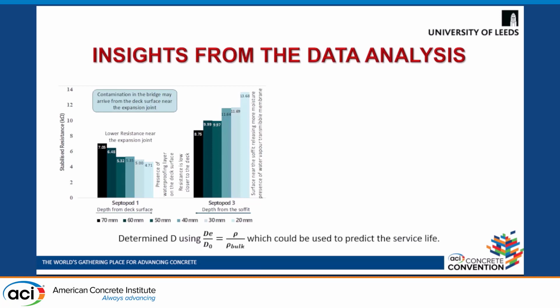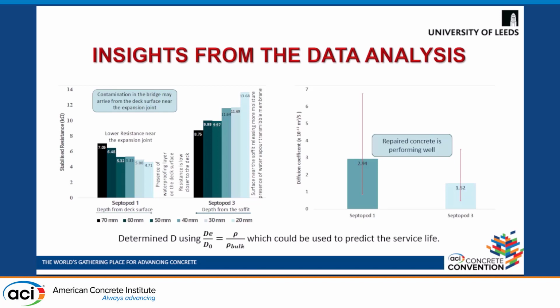Therefore, these obtained values of stabilized resistance can now be used in the equation D by D naught is equal to rho by rho bulk, which is used to calculate the diffusion coefficient, which can be used further for predicting the service life. The values obtained for the diffusion coefficient lie in the range of 1 to 3 times 10 raised to the power minus 12, implying that the repaired concrete is performing well. However, if contamination were to arrive, it may arrive in the bridge from the deck surface near the expansion joint, because this location has a higher diffusion coefficient value.